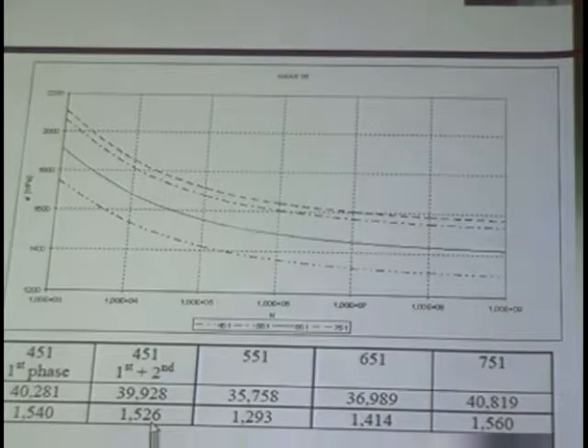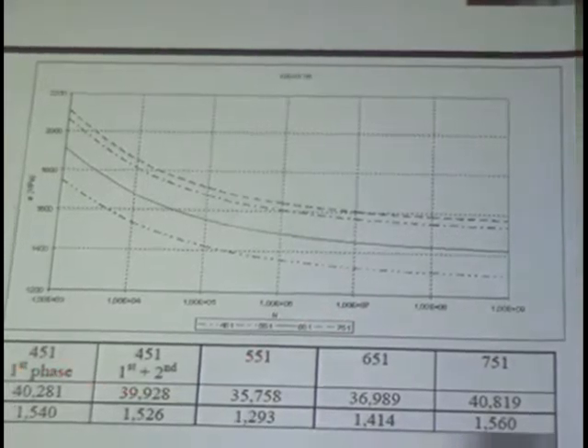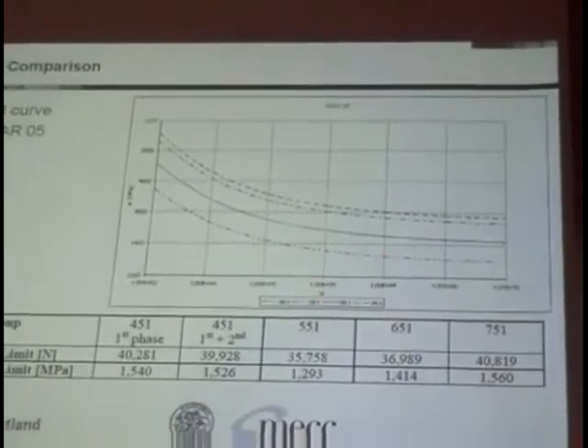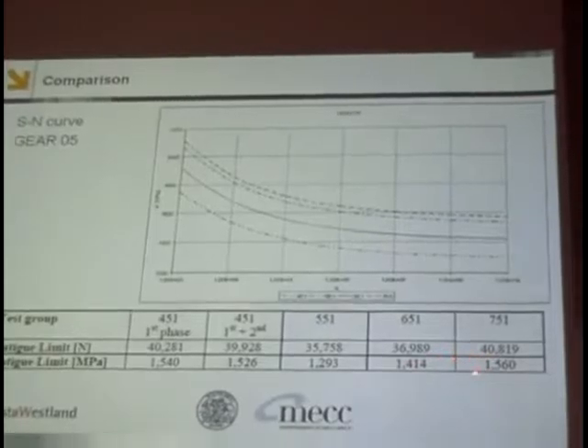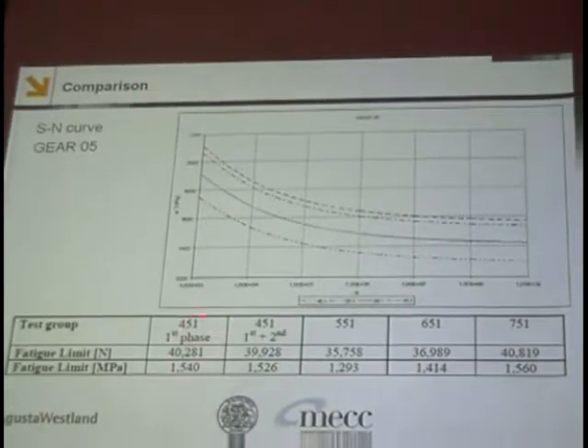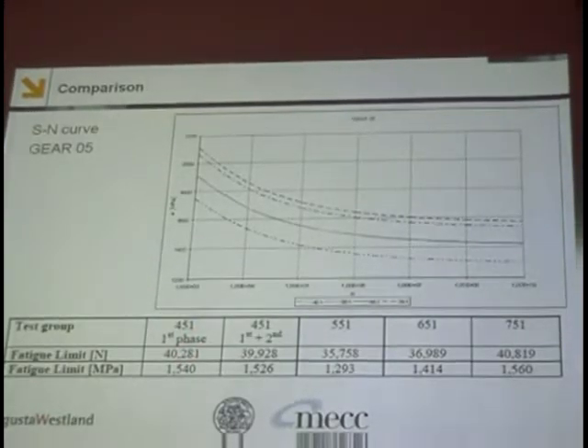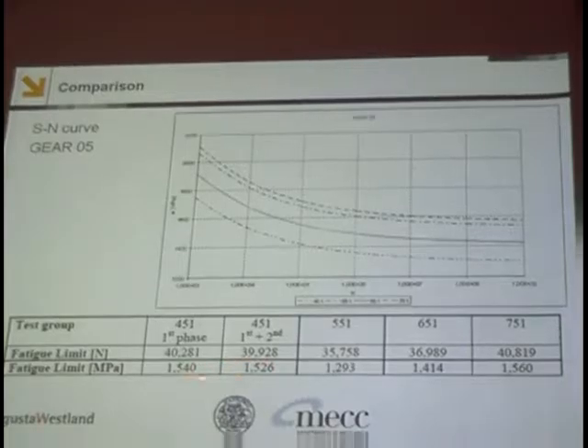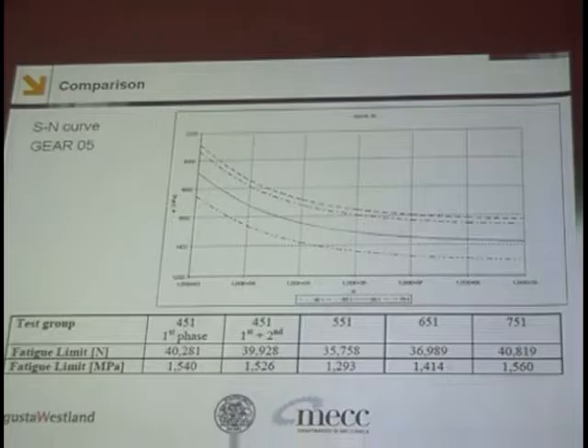So just a final comment. This is a special curve which is currently employed by the industry, but we don't suggest they use this data. But you can compare the so-called fatigue limit. Well, it's an endurance limit at 10 power 7 between the different conditions. So in the first phase, we considered just the tests up to 10 power 7, and in the second phase, we considered also tests up to 10 power 8. And we have a small difference, which has to be attributed to the way we perform the data fitting, not a real or a consistent reduction of the fatigue limit between the 2 test sets.